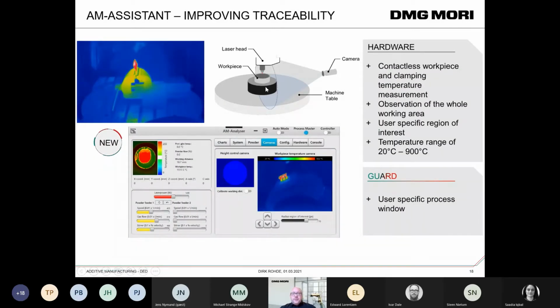And we have two temperature checks. One check is here on the top left. We are checking the heat impact into the part and into the clamping, as well as into the table, so that the operator and everybody knows how the heat impact into the clamping is. In this case, it says yes, no. The heat is not too bad, but as soon as the heat goes tremendously into the table of the machine, then you would have to stop the machine. And we have melt pool monitoring with a self-adjusting leveling of the machine during the process, and you can adjust your speed, your gas flow, as well as your laser power on the operator panel during the process.